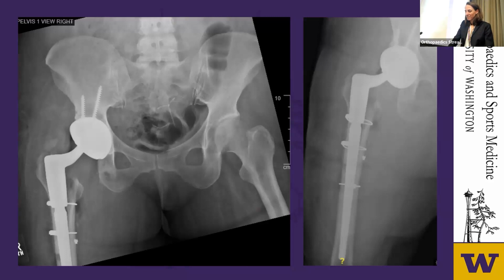Yeah, well, it looks like, I mean, I agree with revising both parts. I don't have a lateral view to see what the version of the cup is, but the femoral stem looks like it's well fixed. It looks like there's useful restoration of length and offset, maybe slightly more offset than the other side, but that's not a bad thing in the setting of the instability type of case. I'm not a big fan of dual mobility, although this is not an unreasonable indication in somebody who's had multiple failed attempts at revision for recurrent dislocation. Probably the very first time, I think that component revision would have been indicated, and they didn't have all those other failures. I probably would have used a large head.